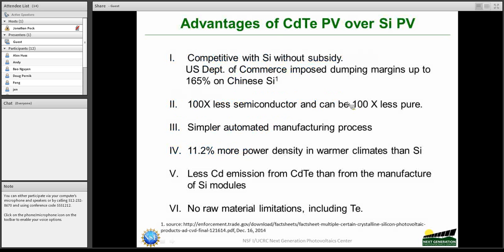So here we are looking at the advantages of cadmium telluride photovoltaics over silicon PV. And cadmium telluride competes effectively with silicon even when silicon is subsidized. The estimate from our U.S. Department of Commerce is that they have imposed dumping margins up to 165% on Chinese silicon, and here is the reference for that from government sources. So that's roughly how much there is subsidy of silicon in the PV industry.